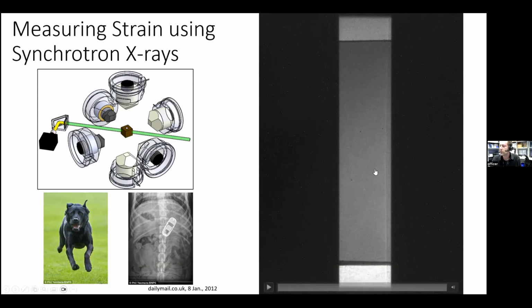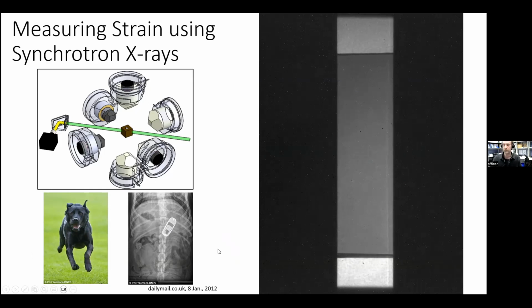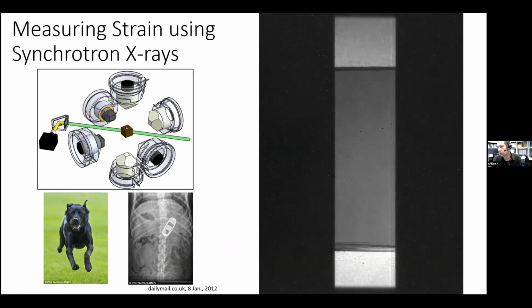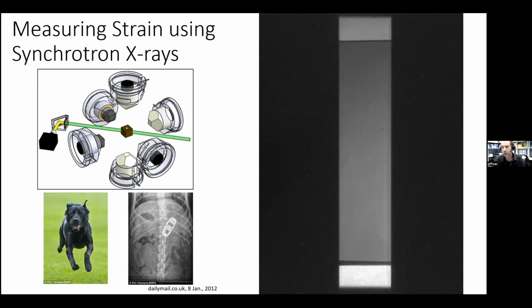But in our experiments here, the sample is gray. You have platinum foils so that you can see the edge of the sample. So you're measuring the length of the sample and seeing how the length changes. And then you have alumina pistons on the side here. As you're deforming the sample, it gets smaller in this direction because you're pushing on it. So we can measure the strain.